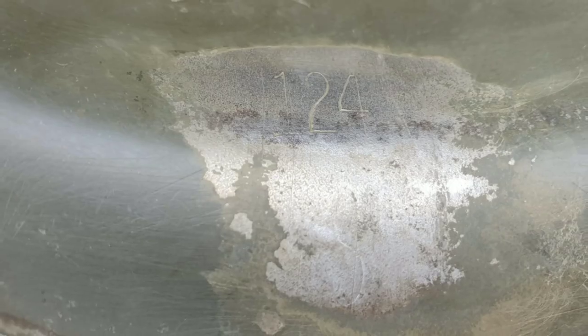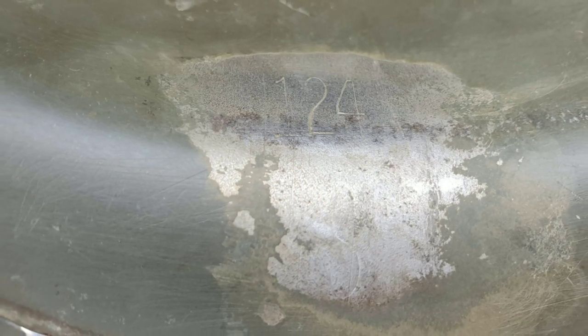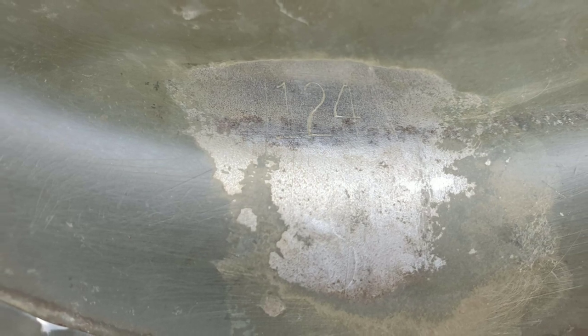Prior to staging helmet steel to the production floor, a quality inspection was performed on sheets to verify their ability to accept the necessary deep draw without breakage. The helmet discs of each lift were required to meet the prescribed bend, magnetic, microscopic, and ballistics test specifications as first outlined in Spec AXS 645 and later in Spec AXS 1170. Discs that passed inspection were delivered to a small punch press where each was embossed with a fine line stamp.